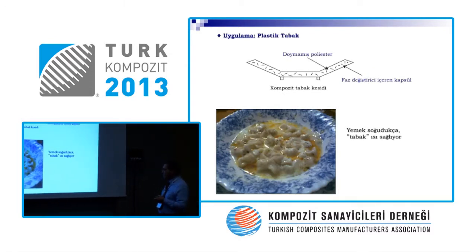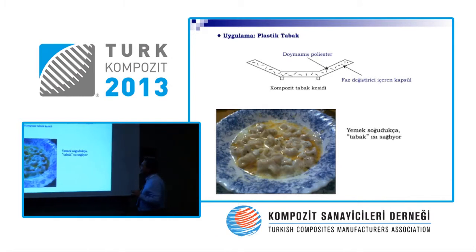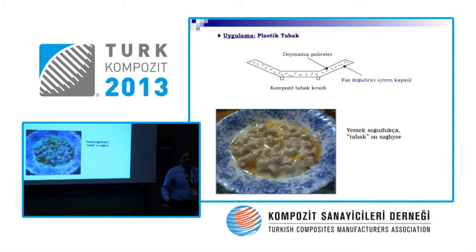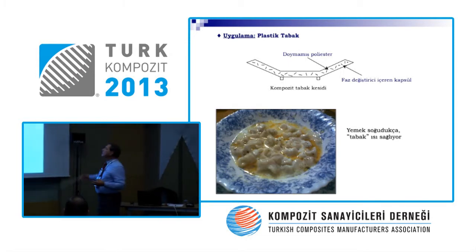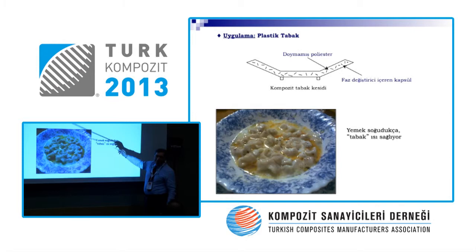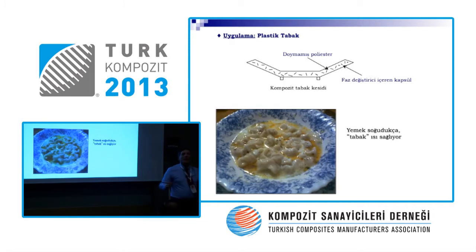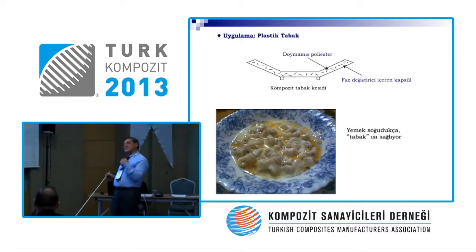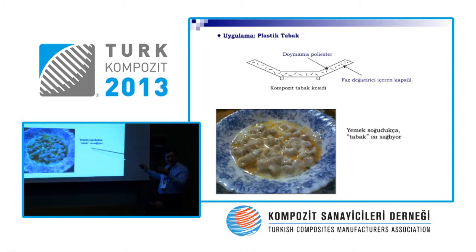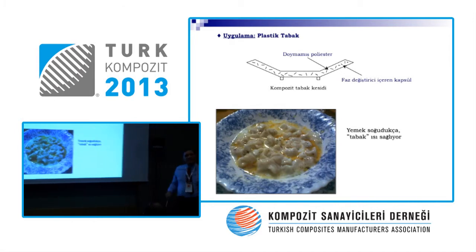We have actually made a plate for a hospital, I'm not going to give the name, and they had complaints that the food from the kitchen cools down until the dishes go to the patients. So we have the plate here, with capsules inside. The plate has been heated up to 60 degrees, and the food is put inside. They go on carts to the fourth and fifth floor, and while traveling, the food cools. When it reaches 50 degrees, of course, the liquids in the dishes here do get solid, and as the food cools, the plate is giving heat to it.